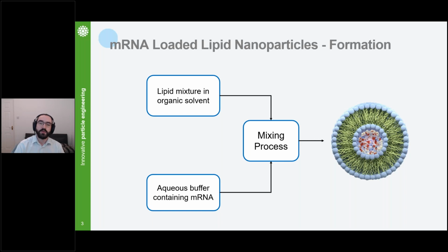That results in our lipids precipitating out. And as a result of that precipitation, they can entrap some of the aqueous material. Even in the case of mRNA, the opposite charges on the mRNA and on the lipids cause those to essentially be drawn together and form those lipid nanoparticles around the mRNA. And that is essentially the process that is being used today for the creation of the vaccines that I've certainly been injected with, and obviously countless others as well.